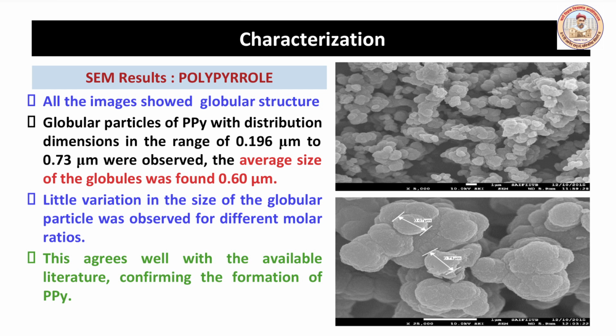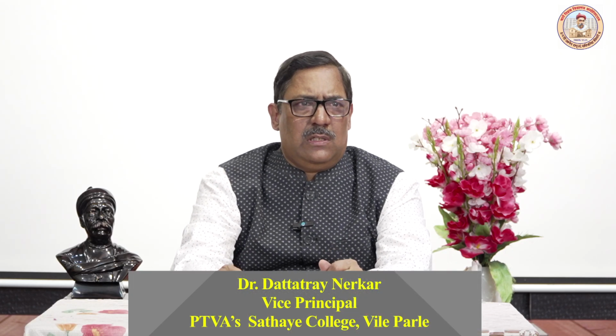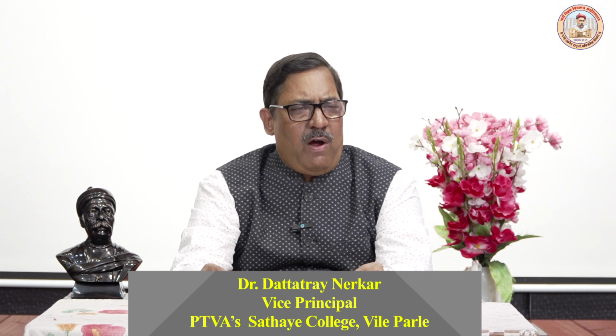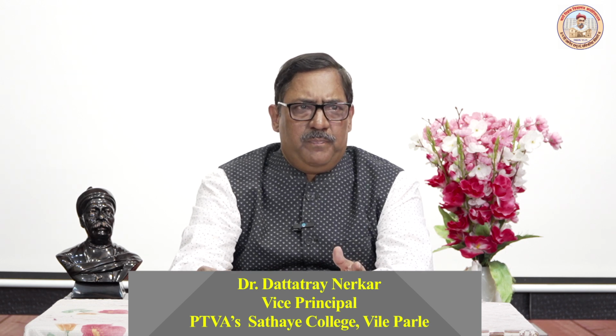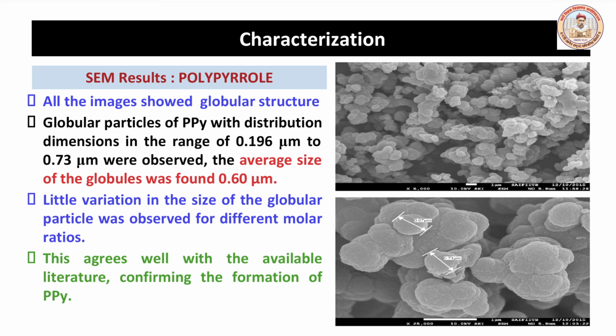Here you can see the SEM images obtained of polypyrrole. All the images showed globular structure. Globular particles of polypyrrole with distribution dimension in a range of 0.196 micrometer to 0.73 micrometer were observed. The average size of globules was found to be 0.60 micrometer. Little variation in size of globular particles was observed for different molar ratios. This agrees with the available literature confirming formation of polypyrrole.